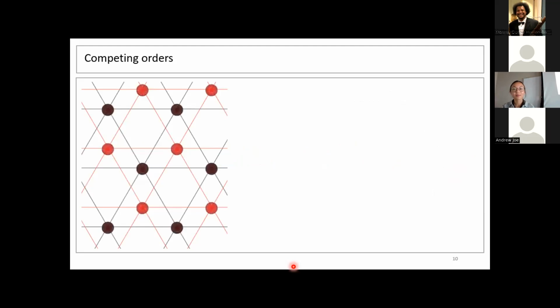And so just to step a little bit into the weeds for a second, you might be wondering, how is it even possible at such a small difference? Because this is going from Fe0.31NbS2 to Fe0.33 to Fe0.35. How can these tiny differences lead to a total change in what even the preferred order is? It turns out that it comes down to some really fine details of the strength of the preferences to anti-align with your neighbors.